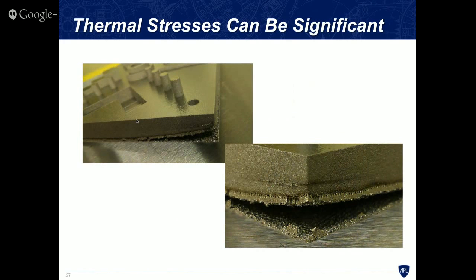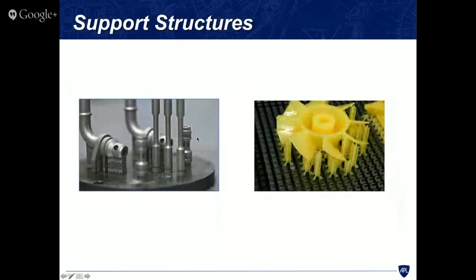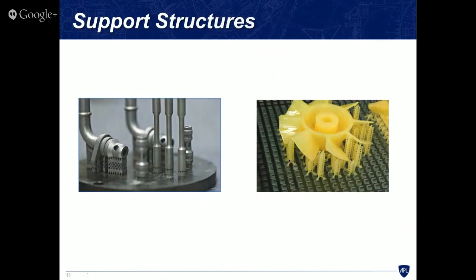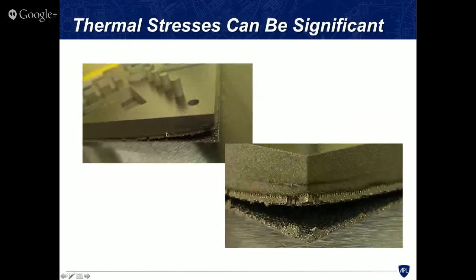So we have a build plate here and we've fused our part. Our part is fused to this build plate, and this is after the part has been done. And you have these support structures in here that help hold the part. Support structures are things like this. They're aspects that you add to your part to hold it to the build plate, especially in the case where you have overhangs or things that might sag during a build. But in this case, we did not make the support strong enough, and the residual stress in the part was too great, and it bent up a corner. This is a metal part, by the way.